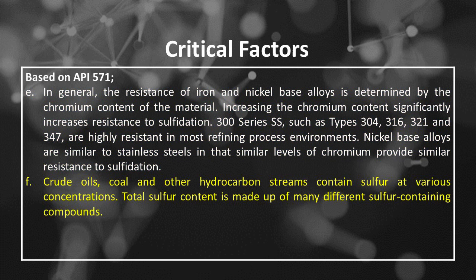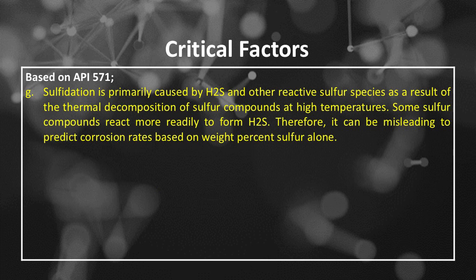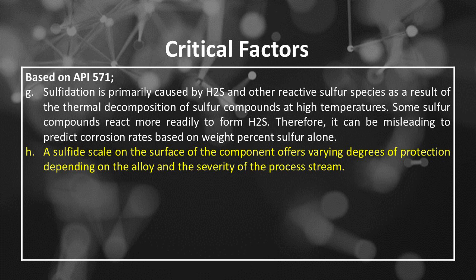Number F, crude oils, coal and other hydrocarbon streams contain sulfur at various concentrations. Total sulfur content is made up of many different sulfur-containing compounds. Number G, sulfidation is primarily caused by H2S and other reactive sulfur species as a result of the thermal decomposition of sulfur compounds at high temperatures. Some sulfur compounds react more readily to form H2S. Therefore, it can be misleading to predict corrosion rates based on weight % sulfur alone. Number H, a sulfide scale on the surface of the component offers varying degrees of protection depending on the alloy and the severity of the process stream.